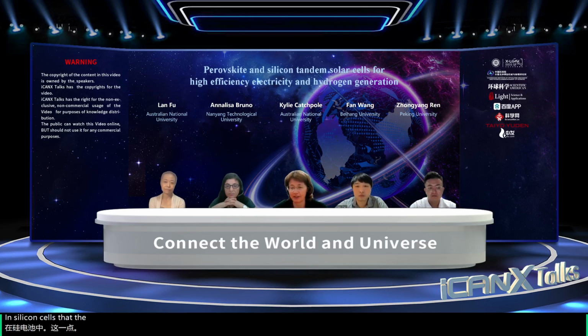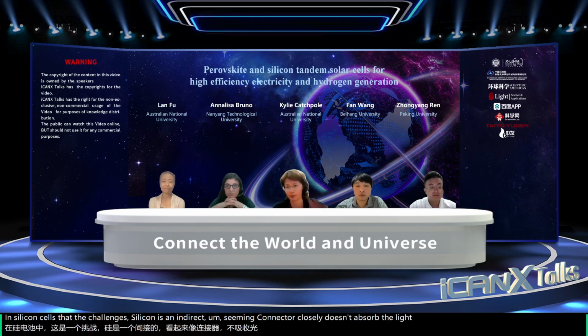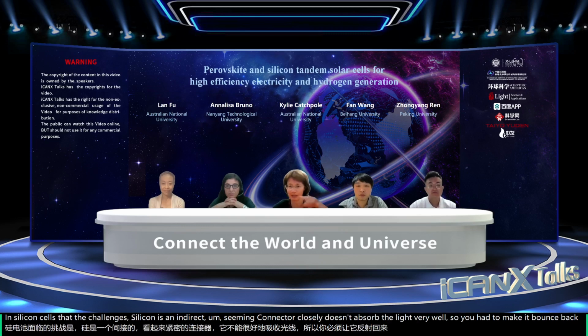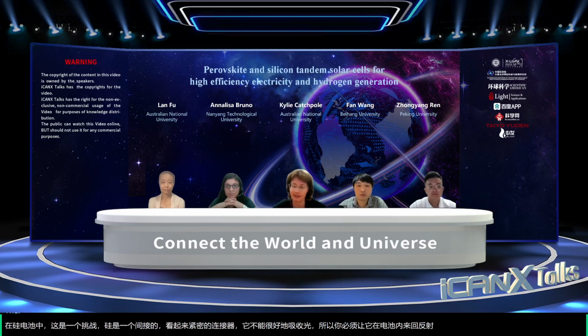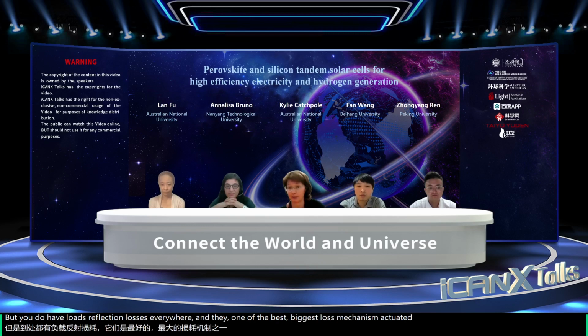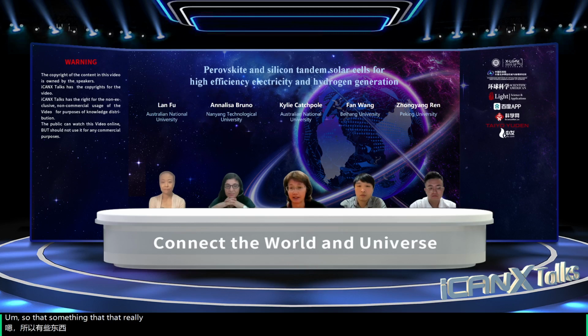The challenge is silicon is an indirect semiconductor, of course, so it doesn't absorb the light very well. So you had to make it bounce back and forth inside the cell. The perovskites are direct semiconductors, so just a few hundred nanometers will do to absorb the light. But you do have those reflection losses everywhere. And they're one of the biggest loss mechanisms, actually. It's where you're losing a lot of the current. So that's something that really does need to be addressed better.